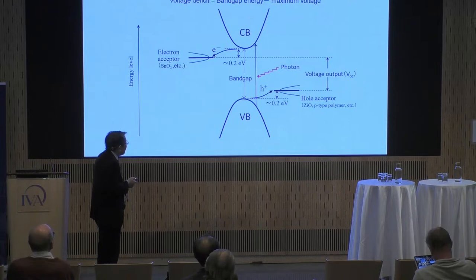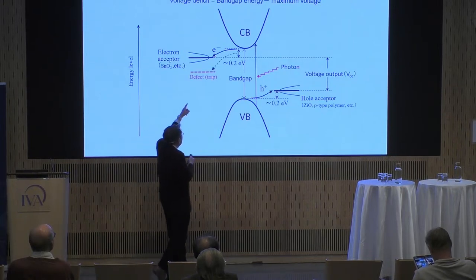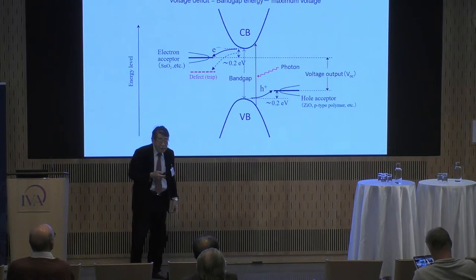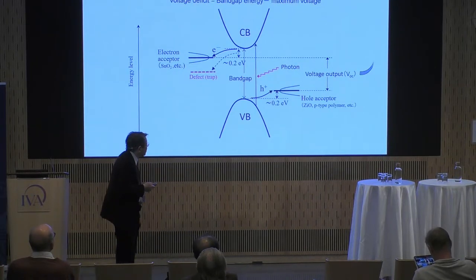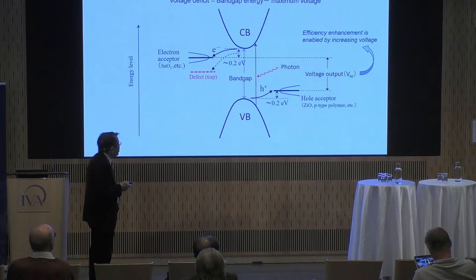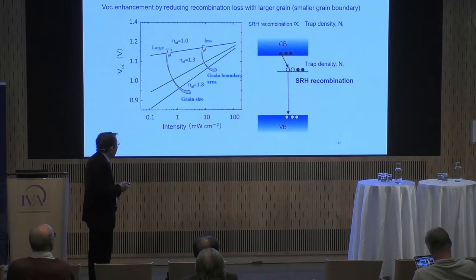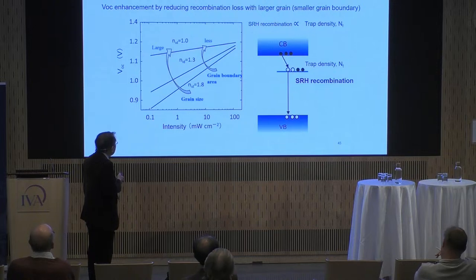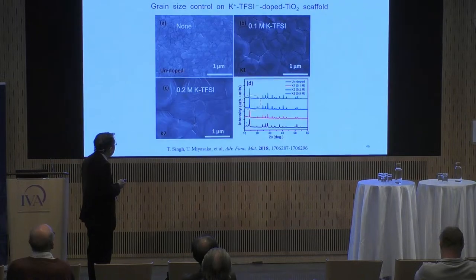Very fortunate element is the voltage is very high, because this voltage loss in the band gap is relatively small for perovskite. But the defect, by minimizing the defect, we can further increase the photovoltage. Now we are focusing on how to enhance the voltage by tuning the grain size, increase the grain size, that indicates the decrease in the grain boundary area.